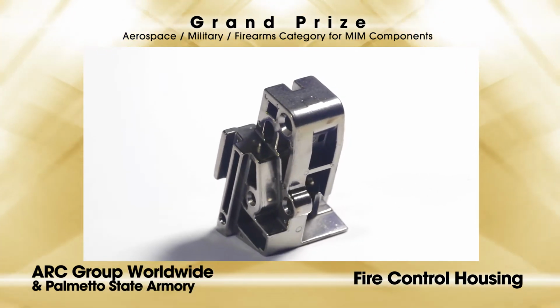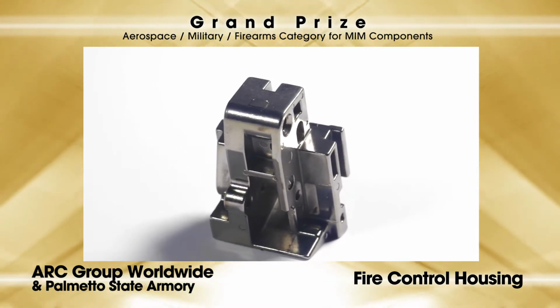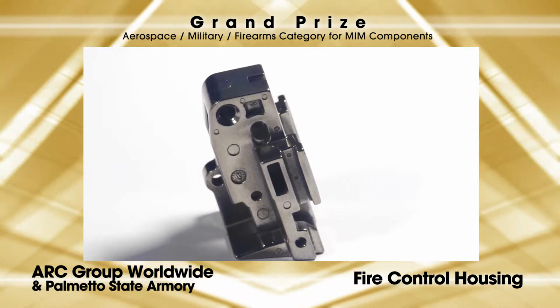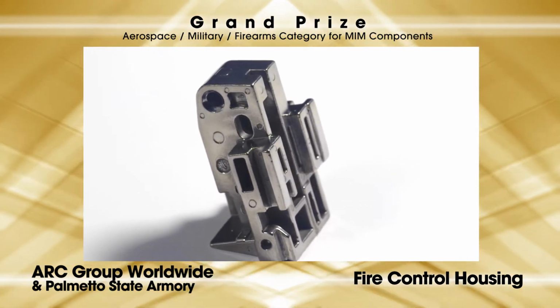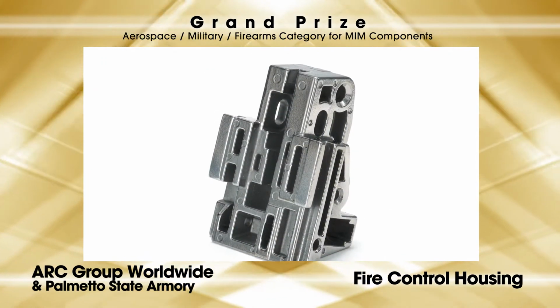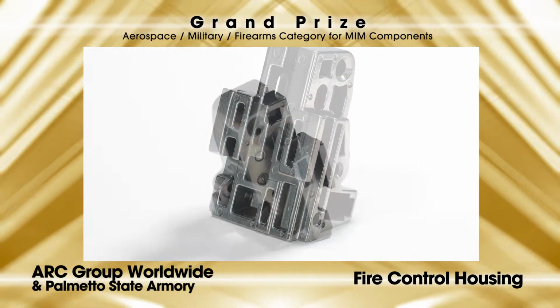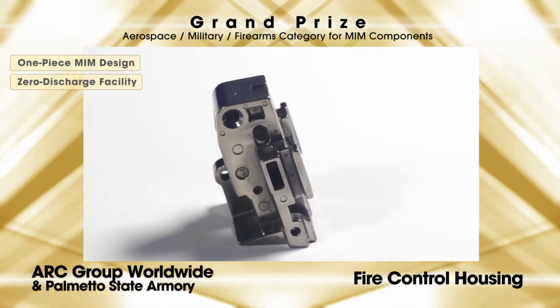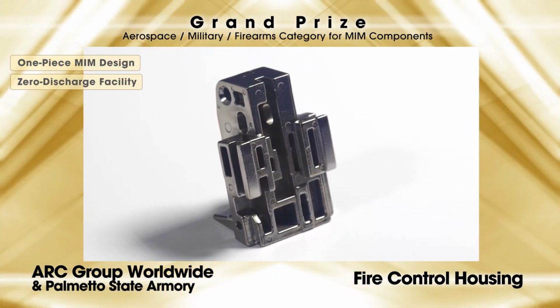The housing features a date code, multiple through holes, and a strategic gate location on the back of the component to maximize material flow. Constrained tolerances on the rib features were critical to control, necessitating a synergy between tooling strategies and sintering tray design to eliminate the need for sizing. Several through-hole diameters are designed to plus or minus 0.04 millimeter tolerances. The one-piece MIM housing fulfilled the function of multiple parts. All sprues and risers are 100% recycled in a zero-discharge facility where no wastewater is released into the environment and air quality is closely monitored.